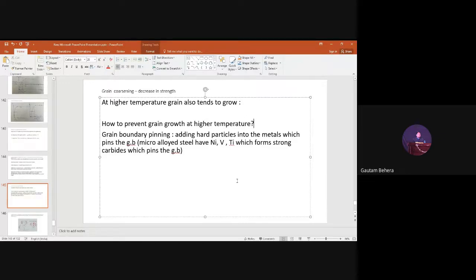So vanadium, niobium, titanium, they form strong carbides and strong nitrides, and the melting point of these carbides and nitrides are very high. They will not become soluble in the matrix at high temperature. They remain stable at high temperature. So what they basically do is pin the grain boundaries. The moment they are pinning the grain boundaries, the grain boundary cannot migrate or grow into bigger size. So pinning of the grain boundary increases the strength also at high temperature. It is called grain boundary pinning by these particles, carbides and nitrides of vanadium, niobium, and titanium.